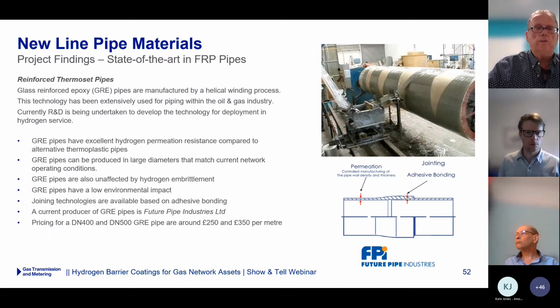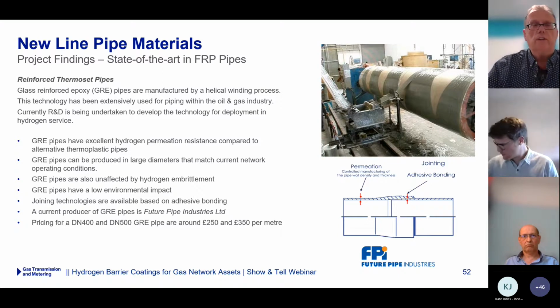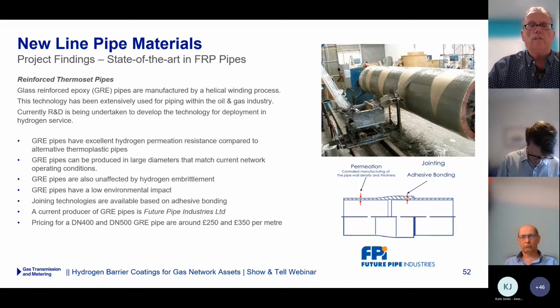So, in terms of reinforced thermoset pipes, as I said, glass reinforced epoxy pipe is probably the method that is being used currently most in the oil and gas industry, and can also be adopted quite easily for hydrogen service. This is done by helical winding, which you see in the picture here. Basically, you wind strands of fiber which are impregnated in epoxy resin around the mandrel up to the thickness that is required to withstand, let's say, the pressure.